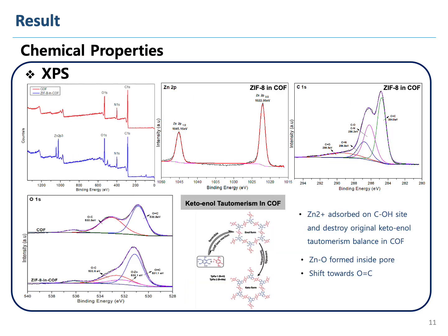Next is the XPS data. We can see from the full spectra the presence of nitrogen, oxygen, and carbon in COF and an addition of zinc in ZIF-8 in COF. We can further confirm the presence of zinc from the high resolution XPS of zinc in ZIF-8 in COF, and also from the carbon high resolution XPS, we can see C=N and C=O form, which indicates the successful synthesis of ZIF-8 in COF.